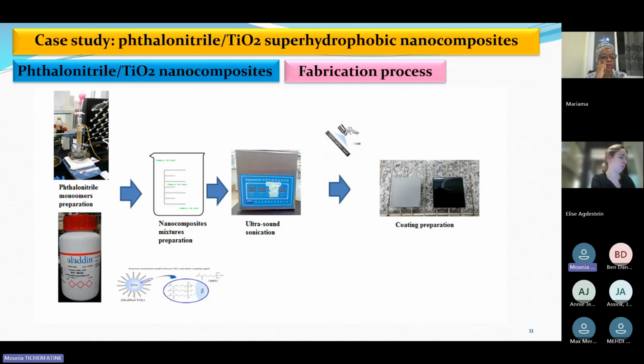Here, nanocomposites were prepared by adding the necessary amount of the treated nanofillers, ranging from 2 to 6% in increments of 2%, into a glass vessel containing a dissolved phthalonitrile resin. To ensure much better dispersion of the titanium nanoparticles, the mixture was vigorously stirred using a mechanical agitator and then sonicated. The selected substrate used to assess the corrosion protective properties was a carbon steel panel. The deposition of the nanocomposite mixture described above was performed by a spray coating process. The final thickness of all coatings was about 120 micrometers.